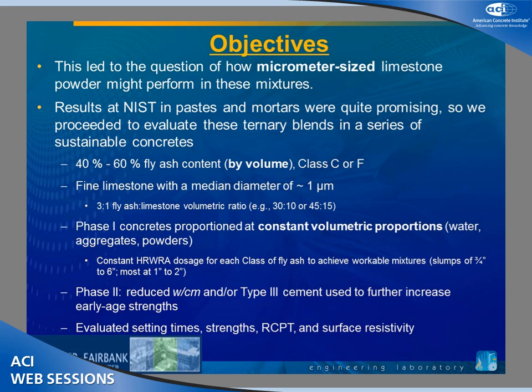Our early age strengths in some cases were still low, so we went to a phase 2 where we took the typical approach of reducing the water cementitious materials ratio, and we also switched to a type 3 cement to increase early age strengths, just like the industry has been doing for years. You might wonder, I'll just make a side comment about type 3s and setting times. Type 3 cement, if you switch in a high volume fly ash mix, it will help your setting time.